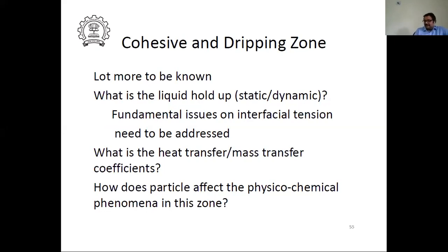This is something interesting which we are doing experiments on also. Very fundamental experiments, so these are far away from the industry, but still have a lot of relevance. One of the difficulties in modeling the blast furnace is below the cohesive zone, where you have coke, and you have liquid, meaning metal and slag, and gas going up. Industries want to push the production. Once you try to increase the production, your efficiency will come down and your coke rate will go up. That is true for all systems. When you want to do more, faster, your efficiency will go down.